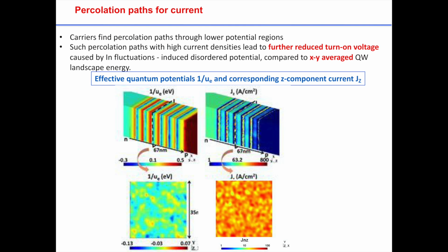But when you do that, what you find in the end, for instance, for, I think, 20 amps per square centimeter on average, which is for a typical applied voltage of 3 volts to your LED, is that the distribution of your current is very inhomogeneous in a given plane of alloy.